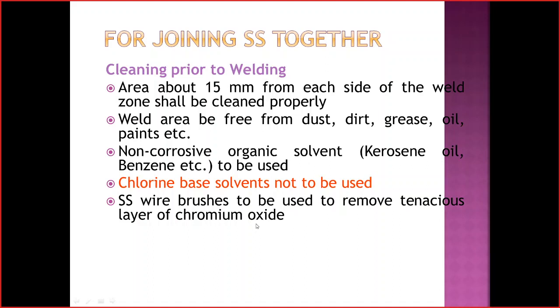Now what to remember is, to clean the surface, if we use an MS wire brush, what will happen? MS will react and will reduce the chromium layer property of this steel metal. So the surface will become roughened and it will attract again corrosion. That is why what we can suggest, we have to use only SS wire brushes for SS welding. Number one, MS wire brushes should not be used on SS.